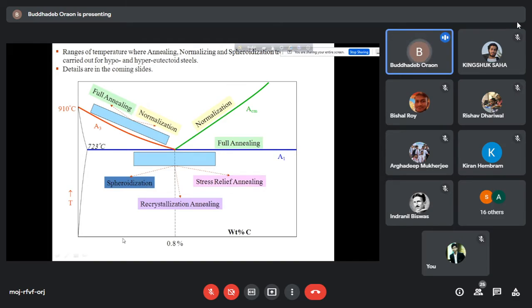So you'll have to come to this particular point at A3. So this is the point. From the y-axis also you can read this temperature. Normally, you will have to heat the specimen around 50 to 60 degrees above the A3 line. That is the temperature at which you have to heat, at a certain rate, and then you have to keep it for a certain period of time, which is known as soaking time, and then you'll have to cool it. If you are performing, say, normalizing or full annealing, then the cooling is air cooling, sometimes furnace cooling also. So that is how you will perform full annealing or normalizing.